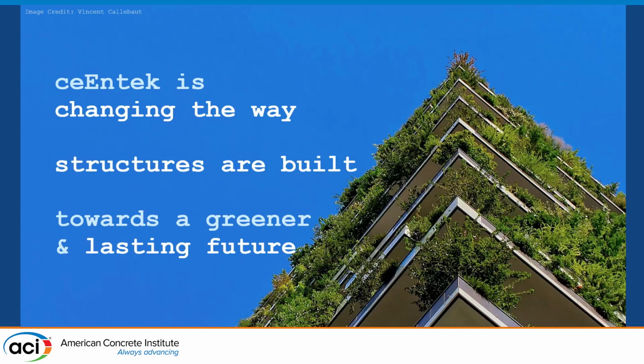So the neat thing, and this is the innovation, this is where ceEntek has kind of cracked the code and done something different, is that these carbon nanofibers are water dispersible. They don't necessarily need the admixture to make them disperse. Normally they want to agglomerate and form little clumps that are still tiny compared to anything else we can think of, but these are water dispersible, so they are going to go pretty much everywhere, and you don't necessarily need that superplasticizer load to go up. And I'm not going to say it doesn't go up at all, because I honestly don't know. That's beyond my pay grade to know that.